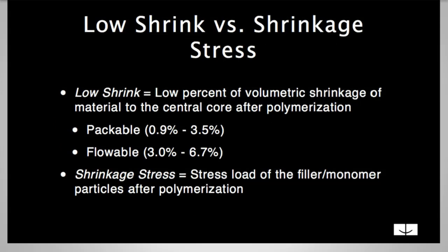What we now know is that shrinkage stress is what matters. How much shrinkage there is, polymerization shrinkage, isn't as important as how much stress is related to that shrinkage. And so packable resins have polymerization shrinkage of 0.9% to about 3.5%. Flowables can be anywhere upwards to 6.7%. But again, the polymerization shrinkage isn't exactly what matters. It's the shrinkage stress.